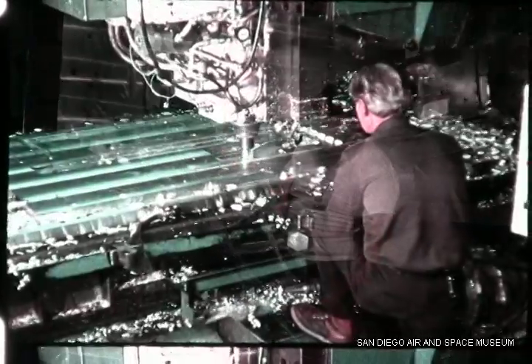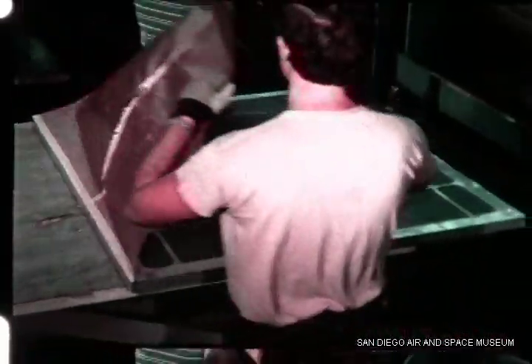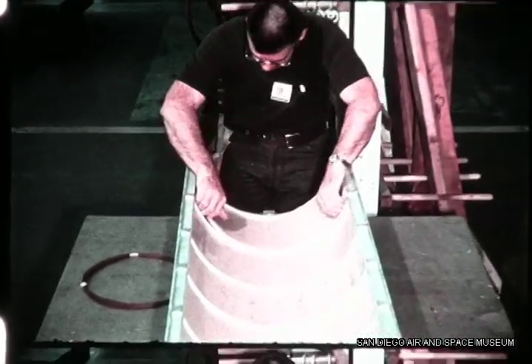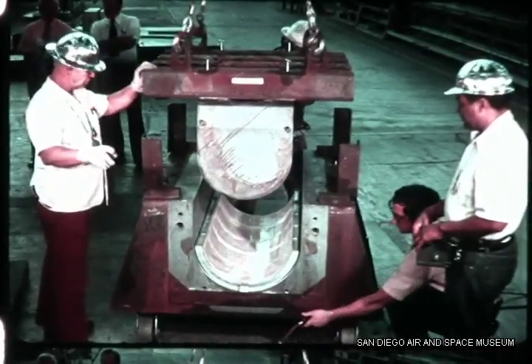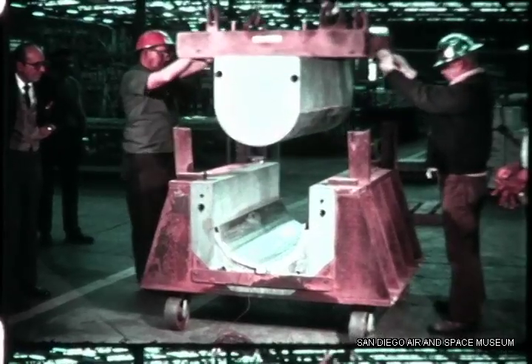The production of body skins involves in the prototype a series of skin machining and rolling processes. The skin is first machined in the flat using numerical control techniques. It is then filled with rigidex to give the upstanding legs sufficient support so that it can be rolled to the contour of the missile. After rolling, the voids are filled with rubber in preparation for the age sizing process. The part filled with rubber is placed in the die and then in the oven for the age sizing. The rubber expands in the die, forcing the skin material against the die, giving us a very good reproduction of contour.